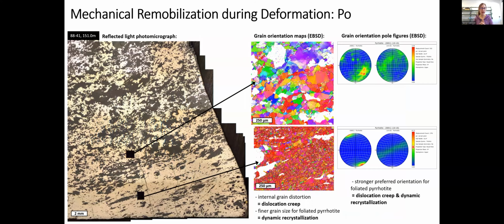So here we have the semi-massive pyrrhotite that we saw earlier. Again, you've got less deformed over here and more deformed over here. In the middle, I'm showing the EBSD microstructure maps of both the coarse-grained, less deformed, and the fine-grained, more deformed areas. And the important thing here is they're both at the same scale. So you can immediately see that the foliated, deformed area is much finer grained.